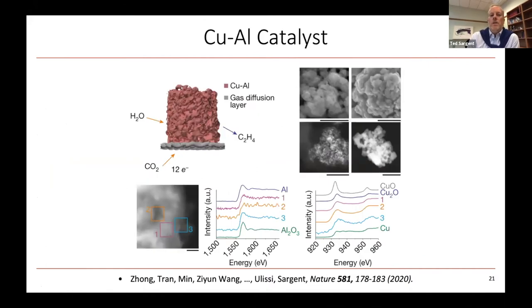We went into trying to develop copper alloy catalysts and actually found quite good results on substantially planar copper alloy catalysts, which we made both by co-sputtering and also by ion implantation of aluminum into copper. But then we actually found something pretty interesting, which is we could do even better if we annealed the copper alloy, copper aluminum alloys, got a little bit of nanoscale phase segregation.